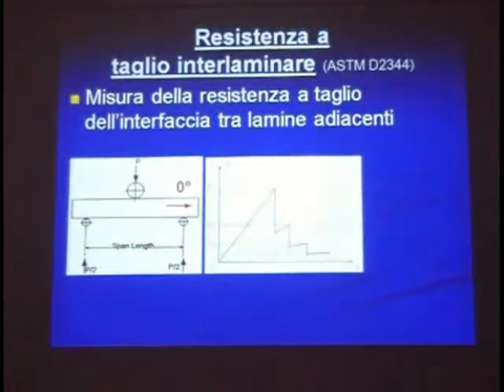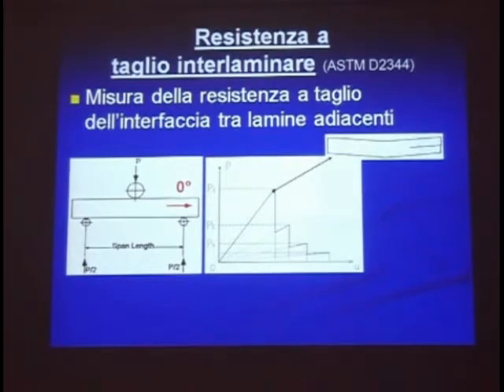We have been using the interlaminar shear strength test, which is basically a flexural test with a very short span in order to have very high shear inside the material. And this gives you delamination usually, and this is the formula that we have been using to calculate the strength based on the load and the sample dimensions.